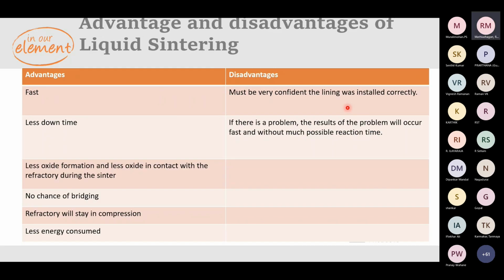When it comes to advantages and disadvantages of liquid sintering, it's fast, less downtime, less oxide formation, and less oxide actually in contact with the refractory during the sintering. No chances of bridging. Refractory will stay in compression, and less energy is consumed actually. But when you talk about disadvantages, as I said before, you must be very confident, and the process has to be taken with utmost care.